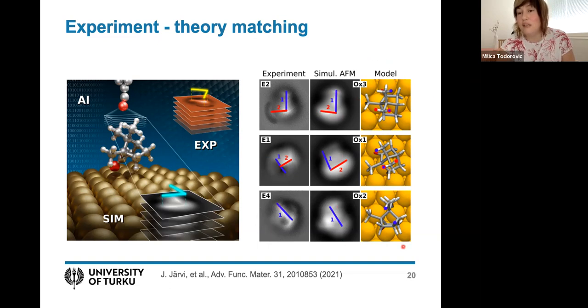And now you can really look at this model of the adsorbates behind these images. And these are one of the lowest adsorption energy structures. And we could really tell which atoms were behind these features. So this kind of identification in experimental images is difficult to obtain without some ab initio structure search, but the ab initio structure search without active learning would have been far, far more laborious.